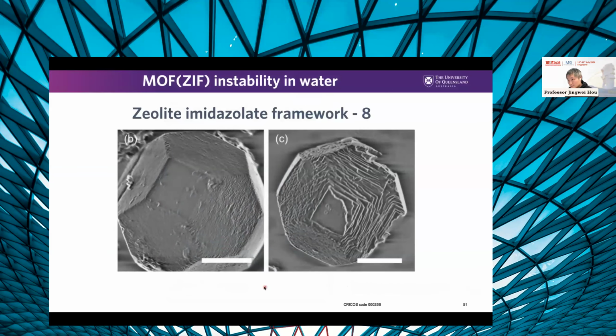Actually, I'm going to show you a few examples. I've been talking about MOF materials for such a long time, but MOF is not perfect. For example, this is the very first MOF I started looking at, zeolitic imidazolate framework 8. It is a good material, zinc-based, low toxicity, easy to fabricate in water, but it's not stable. If we have a single crystal and soak it in water, or expose it in the lab, like in Brisbane or Singapore weather where humidity is really high, we actually see the decomposition of the crystal lattice very quickly. We're talking about overnight.